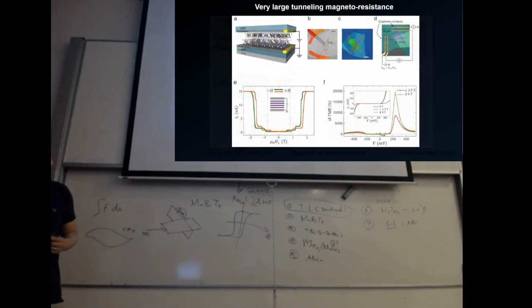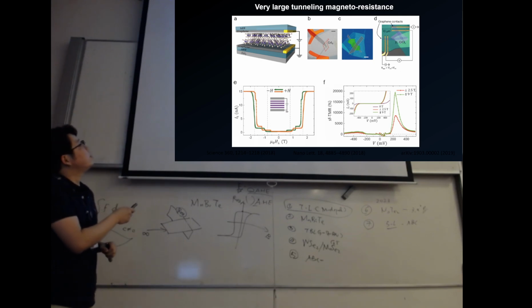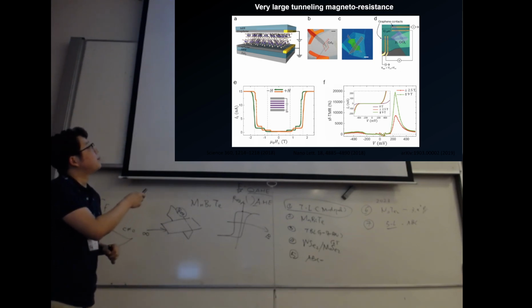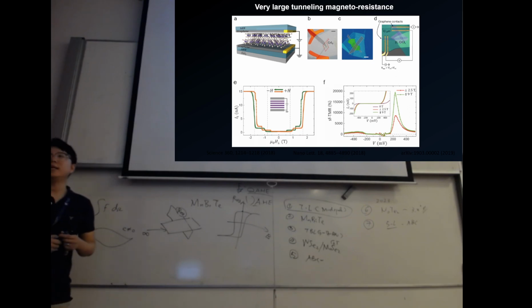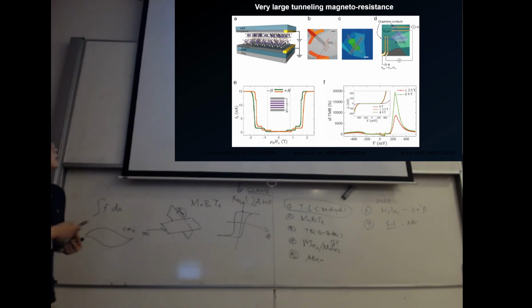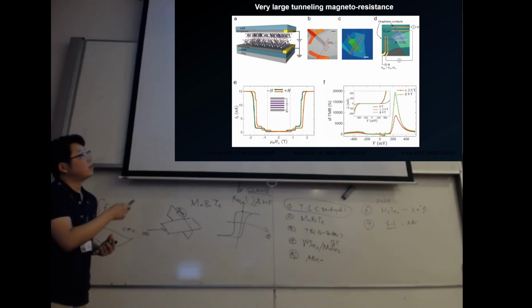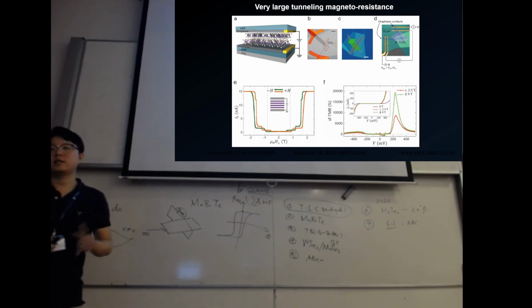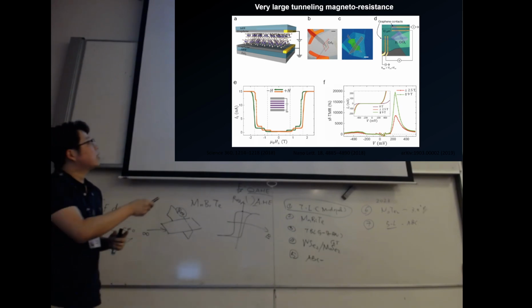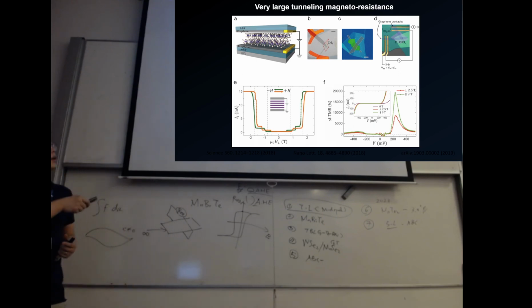And some of them are actually showing huge spin polarization. For example, in this experiment, it's the same material. The monolayer case is a ferromagnet. Two layers is an anti-ferromagnet. In this case, if you put down four layers in a row, with top and bottom electrodes, this is a typical MTJ, magnetic tunneling junction. All right. So there are several steps that switch the spin polarization of each layer. At the end, they saturate toward one direction. And if you calculate this spin filtering rate in TMR, it goes up to like 20,000, which is huge.